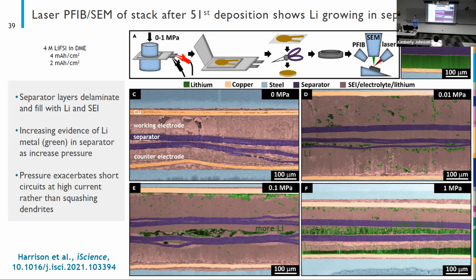Yeah, so we don't measure the porosity. All we measure is the thickness. You could back out a porosity knowing the capacity, although you can't account for SEI very easily in that. So we haven't actually tried to measure the porosity particularly, but we sort of could assume a porosity from the thickness. And he's asking about this slide. He says that the thicknesses of the cells look different.